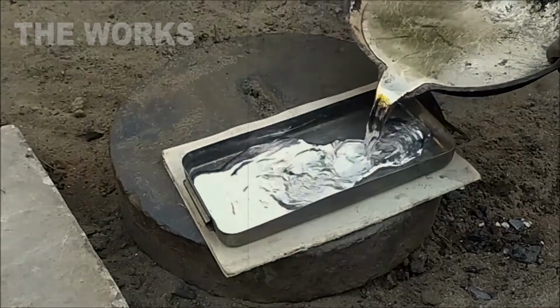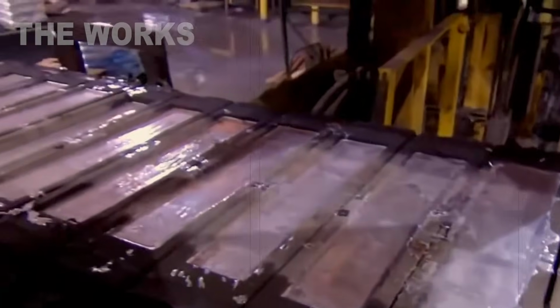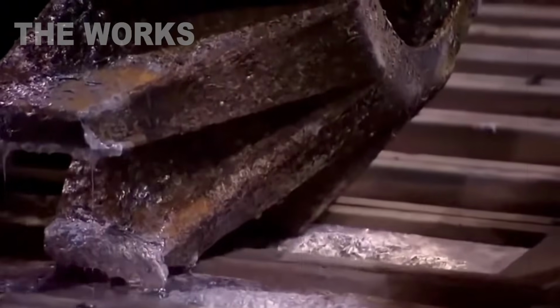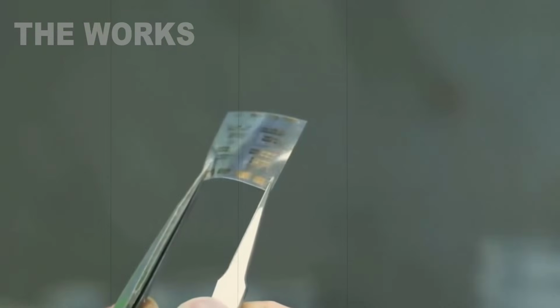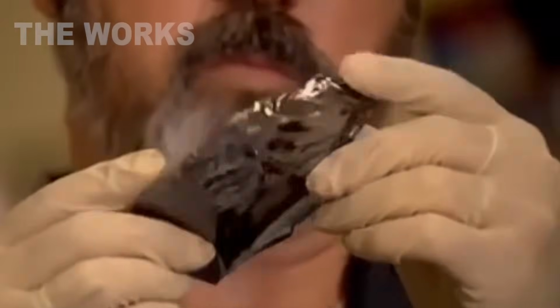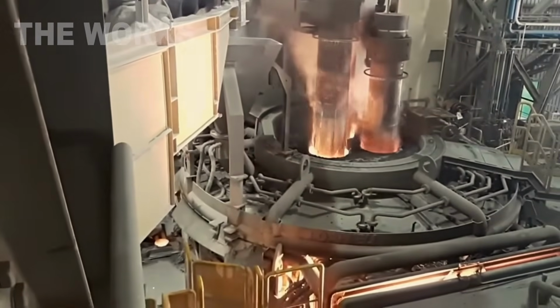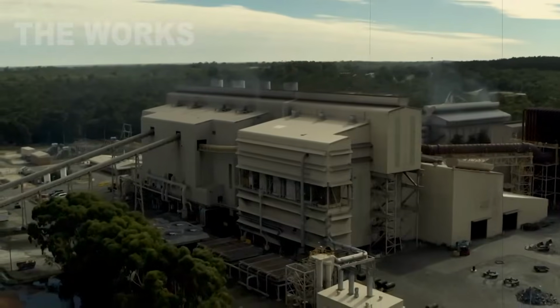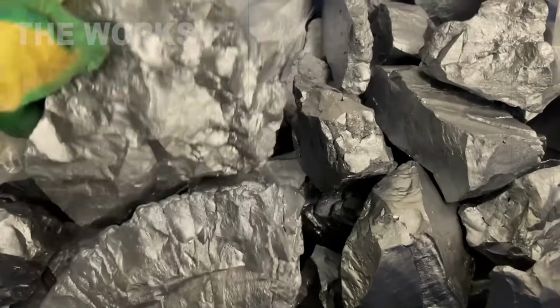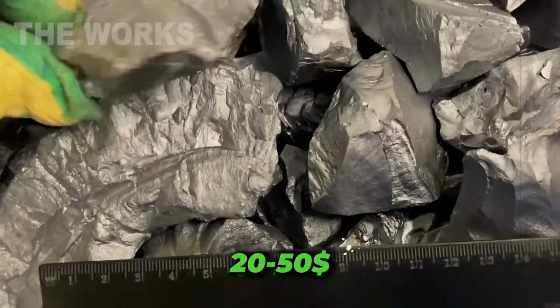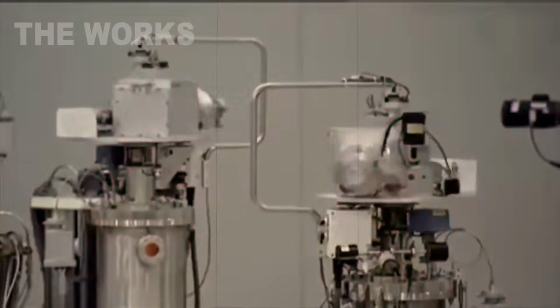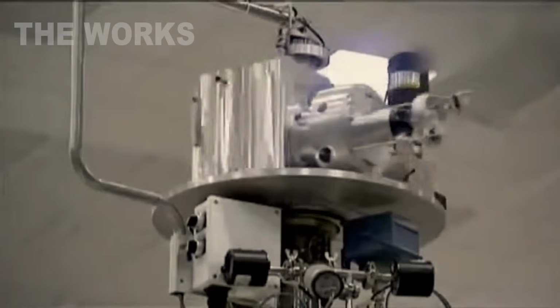In that time, those thin rods grow into thick cylinders up to 8 inches in diameter and weighing up to 660 pounds. They look like giant gray icicles. This is polycrystalline silicon, the purest material humans have ever made. Purity reaches 11 nines, 99.999999999%. A single kilogram of this silicon costs anywhere from 20 to 50 bucks, tens of times more expensive than metallurgical grade. The polycrystalline silicon gets chopped into chunks and shipped off to single crystal manufacturing plants.